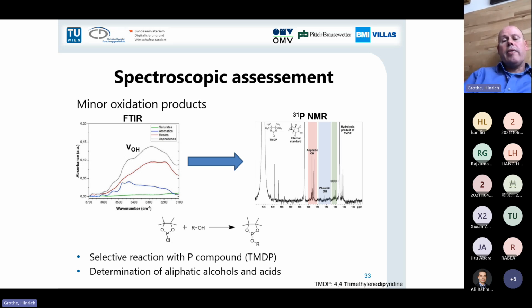A more detailed information I can gather with NMR spectroscopy. And this is a special kind of NMR spectroscopy, because here you react the OH functional group with a phosphor compound, with TMDP, and you form a phosphor ester, and then this phosphor-31 is NMR active, and by this, you can really differentiate different alcohols and acid groups and their position within the material. So this is a very interesting technique, because first of all, you can correlate infrared spectroscopic information and NMR information, and you can, in particular, focus on OH groups and learn where exactly they are situated, and you even can try to quantify that.